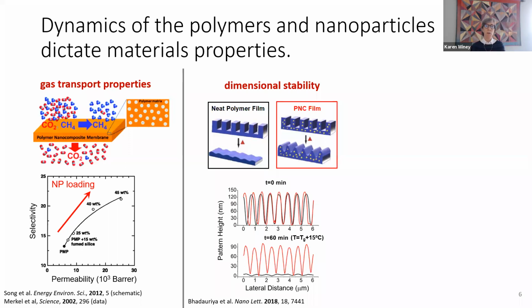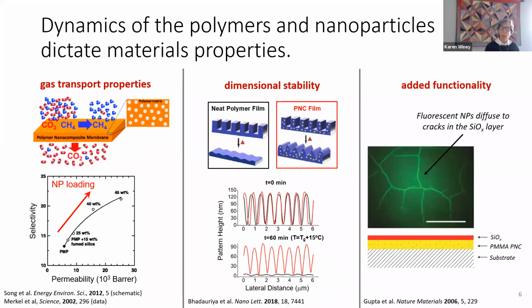This is an example of dimensional stability if you were going to do imprinting to make nanoscale features. If there's nanoparticles in there, you can see this is the unannealed sample, this is the annealed sample. And if there are no nanoparticles there, the whole thing is just flattened out. And if the nanoparticles are there, you maintain the topography, right? So this is a flow, maintaining that shape during the fabrication. And then this is an example where there's a nanocomposite underneath a silica layer. And if that silica layer cracks, the fluorescent particles will migrate to that surface. And that might be good for something.